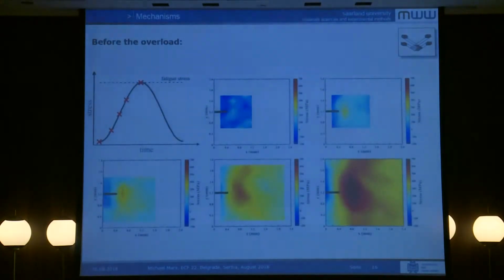And now you can do this not only comparing the unloaded and the loaded specimen, you can do it for different positions in your loading cycle: for the beginning of loading, the mean value of the loading, and also for the maximum amplitude. And then you will get these results by the synchrotron measurements of your applied stresses. So this is before the overload. With the unloaded crack, there are nearly no residual stresses in front, and then you start with your tensile stresses when you start with the loading, as expected, and here you have your maximum load.